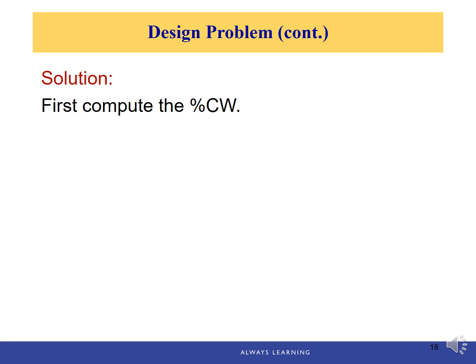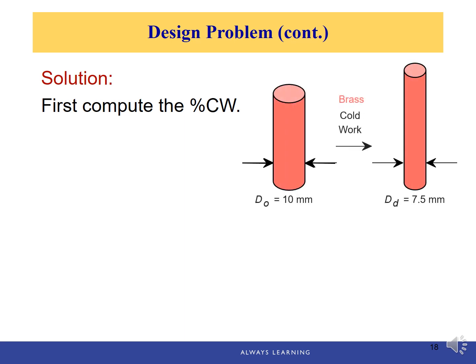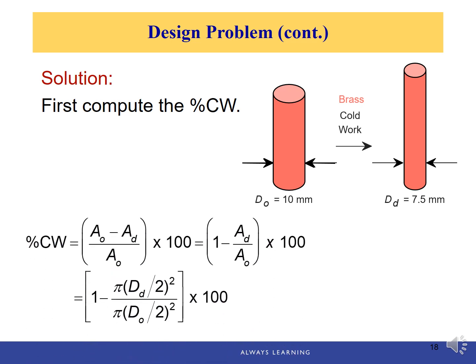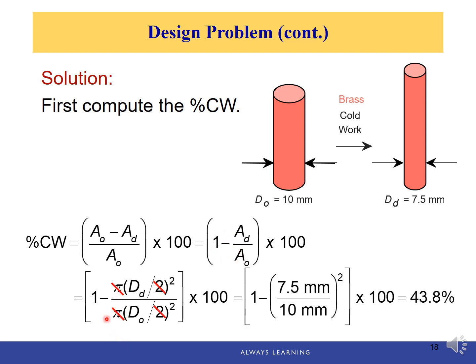First, compute the percentage of cold work. We know the initial diameter is 10 mm, and after cold work, the final diameter is required to be 7.5 mm. The percentage of cold work is defined by the change in the cross-sectional area over the original cross-sectional area, changed to a percentage value. We can rearrange this equation and cancel out the common factors, and it becomes 1 minus the final diameter over the initial diameter, squared, times 100. So the percentage of cold work is 43.8%. If we reduce the diameter just once by one drawing from 10 to 7.5, this is the percentage of cold work.